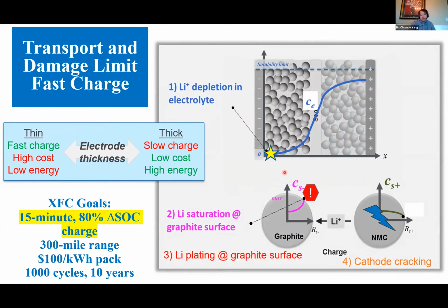Large concentration and potential gradient in the electrolyte phase to support high current result in non-uniform utilization of the thick electrodes. In extreme case, electrolyte concentration approaches zero and shuts off electrolyte utilization near the current collector. This may result in plating and cracking happening near the separator. Second and third, lithium saturation and plating on the graphite surface.